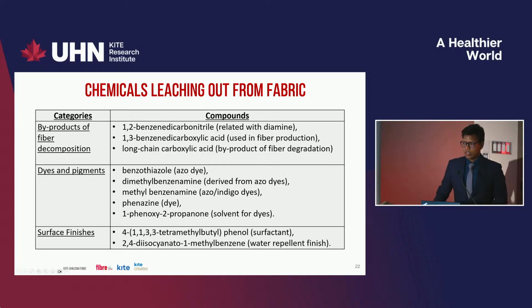And based on our threshold with the available database, we found 70 compounds which are relevant to textile production. But not all 70 compounds are bad, right? But here are examples of a few chemicals which I can explain a little bit. For instance, some of the chemicals we found as degradation byproducts, for instance, the long chain carboxylic acid or the degradation byproduct of the diamine. This came due to the degradation of the fabric. So if we come to the dyes and pigments, we got some chemicals related to azo dyes, and we got some surface finish products. It was very expected that we get some water repellent surface finish chemicals, so we found that.